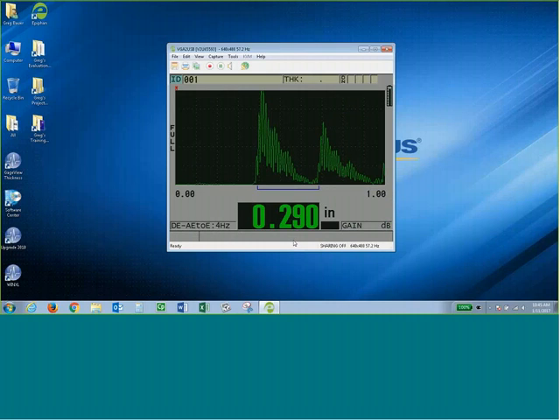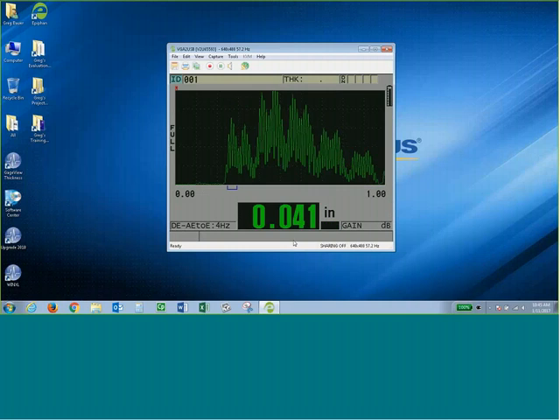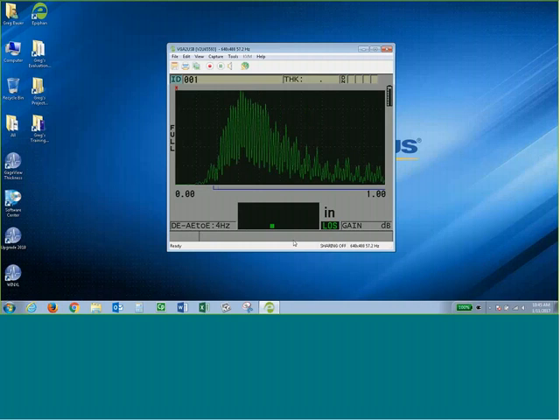here I'm making a valid echo-to-echo measurement between multiple signals. I'm not calibrated, but the reading is close. If I go on the 150, same thing, I'm making a valid echo-to-echo measurement. If I go on the 50, there's just not enough separation. I'm unable to ignore the coating and measure the steel.